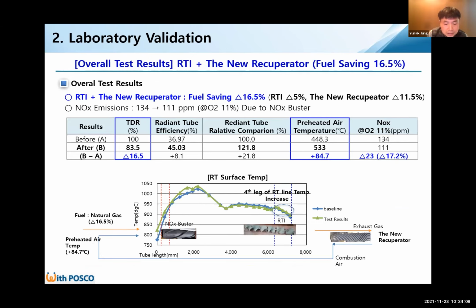I will summarize the overall test result. RTI and the new recuperator bring 16.5% fuel saving, respectively 5% and 11.5%. And NOx emissions were also reduced 17.2%, from 134 ppm to 111 ppm. You can find this in the table. All detailed data explain its energy saving effect and NOx reductions. As a result, preheated air temperature is also increased by 84.7 Celsius degrees.